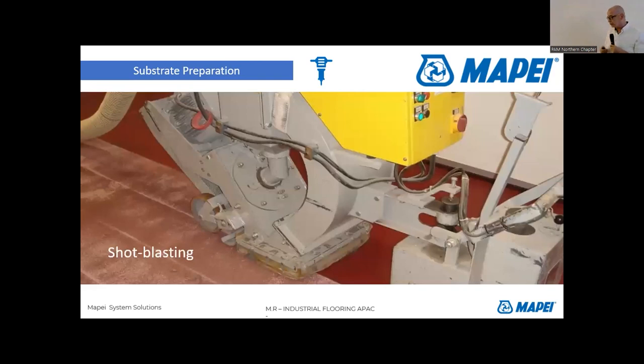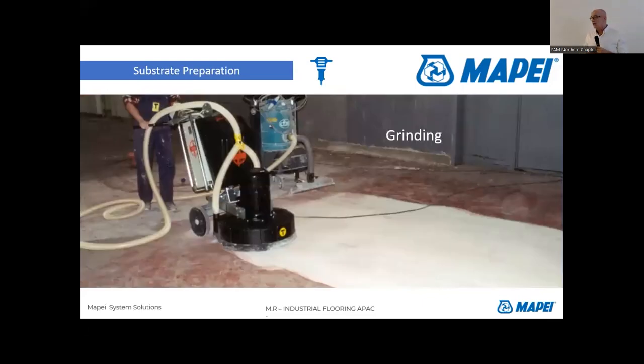So you can see the machine can also remove all contaminated surface or all coatings. We can use a grinding machine, but if you use a grinding machine, be careful. If somebody specifies use a shot blast machine or grinding machine, the grinding machine is one thing. If you're grinding a concrete surface, the pores are closed. You need a very, very good vacuum cleaner to suck these pores open. If these pores are not open, you're grinding and sweeping with a broom a little bit. Nada, it doesn't work. It means the primer needs to penetrate. You need open pores. If you specify grinding, specify vacuum cleaning. Better than 2 times. It means they need industrial vacuum cleaners in order to open these pores.